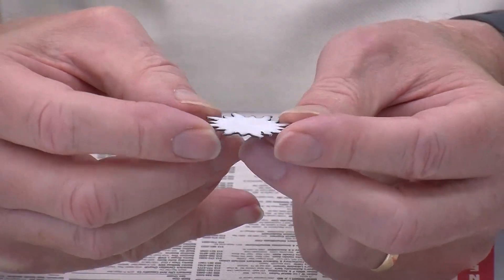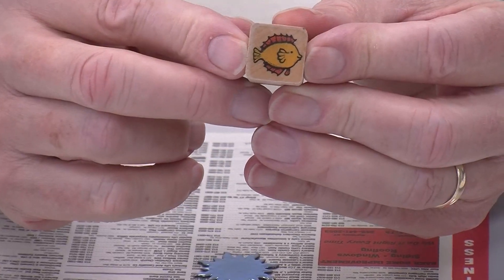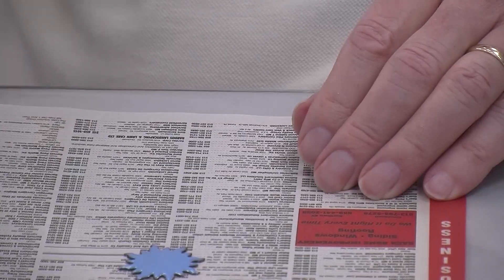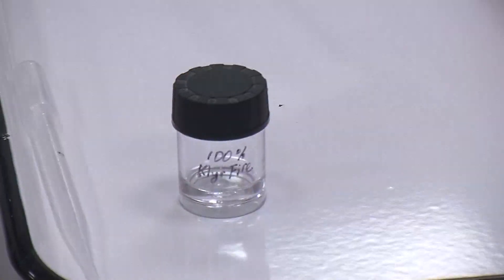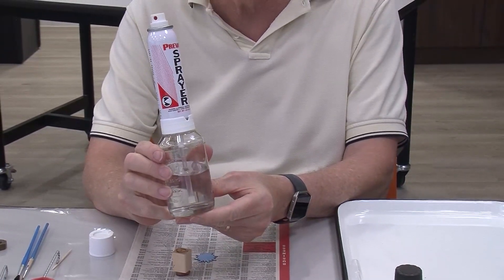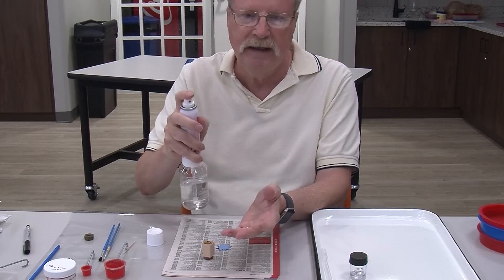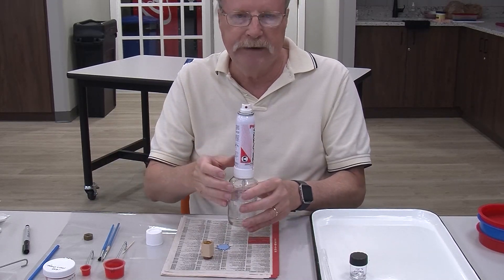I have just white on the back side and a light blue on the front side. What I'm going to do is use a stamp of a fish. This is a technique where you don't have to have any freehand artist skills. We don't actually stamp the glass on with the stamp — we stamp a holding liquid called Klyr Fire. A lot of times you need a holding agent to keep the glass either on the edges or if it's a bowl shape to hold it vertically. This is a mixture of water and Klyr Fire — it's a gum solution. You spray that on the piece, put on the glass, spray it again, dry it on top of the kiln for five or ten minutes, and then that sets the enamel in place.